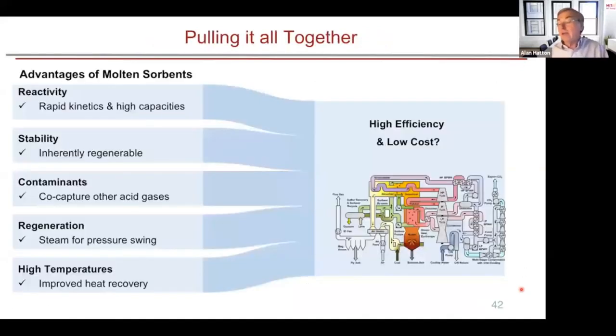So putting it all together, the advantage of the molten sorbents is rapid kinetics at high capacities. They're inherently stable and regenerable. They can co-capture other gases if needed. They can be regenerated by pressure swing or also temperature swing, depending on how we want to go about doing it. And the high temperatures can lead to improved heat recovery in these systems.